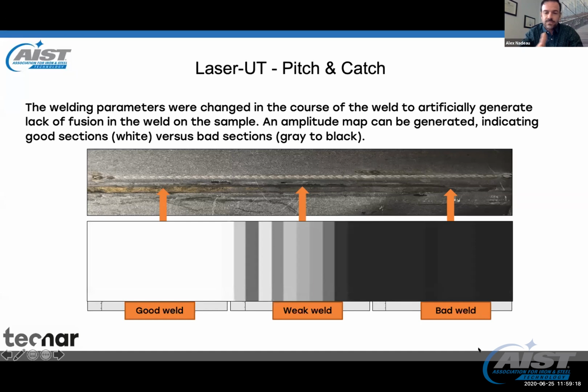You can see that it can be color coded. You can see the laser spots. We can basically generate and detect quite close to the weld itself. So it can be installed right at the welding with the grippers at their standard positions. And it is not affected by the temperature of the strip.